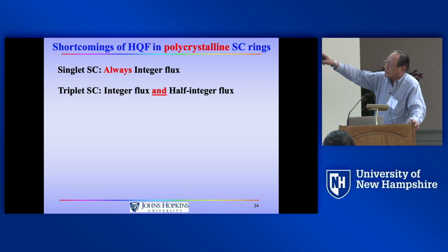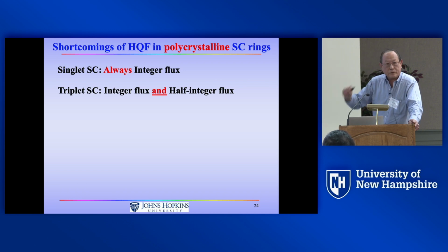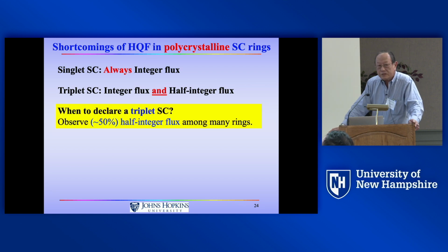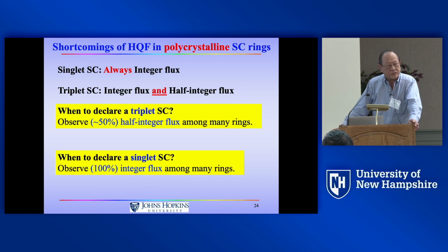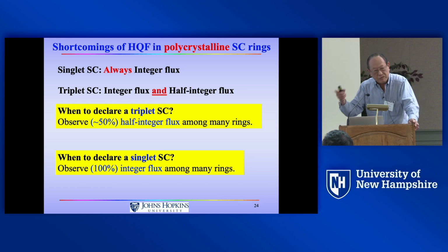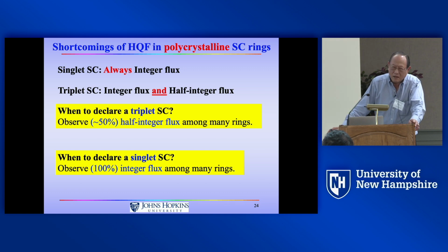Why not? Because singlet always integer. Triplets have half integer, half integer. When do you say you have found a triplet? One ring is not enough. 2 rings is not enough. You at least should do 10 rings or so, and can say, most likely this is a triplet. If there happens to be a singlet, you see 1 ring integer, another ring integer. When do you say it's the integer? I think you need at least to do 10 rings before you can say for sure it's a singlet. I don't like that. I like to do 1 ring and 1 measurement and say it's a singlet or triplet.